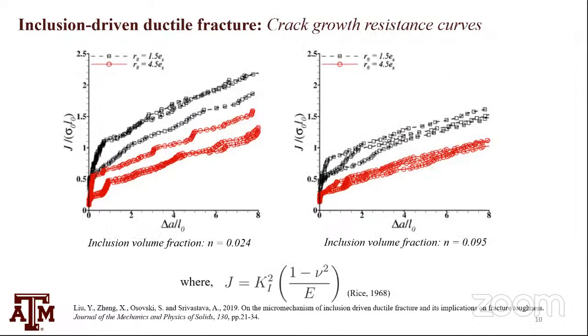We can calculate from these calculations the J-R curve, or the crack growth resistance curve. This is the J integral, the driving force in this case, applied J as a function of increment of crack, delta A. And because we're imposing a K1 field, which is directly imposed, we can follow simple Rice's criteria and get J and plot J-delta A curves for all these cases.